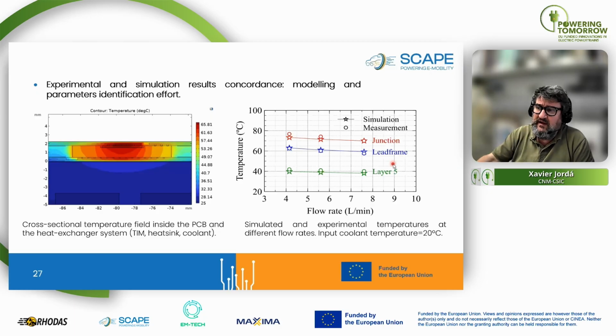And again, one of our main targets was obtaining a very good modeling and simulation of the experimental prototypes that we developed. And as you can see here, we obtained a very good agreement between simulated and measured temperatures versus flow rates at the different measuring points of the switching cell.